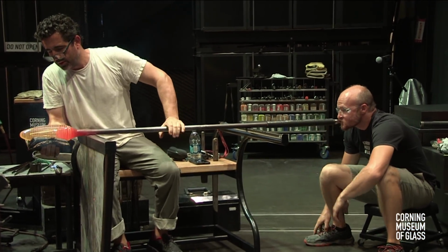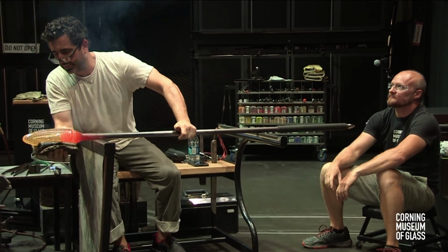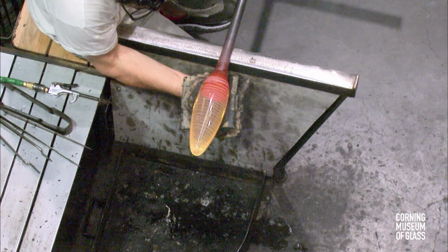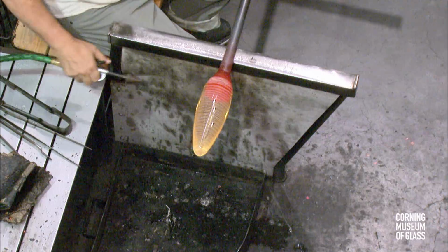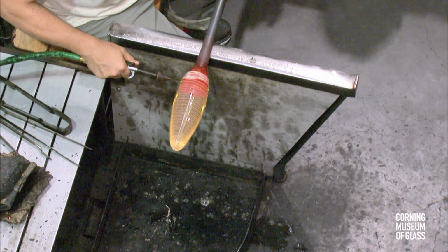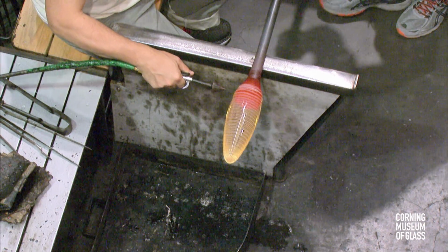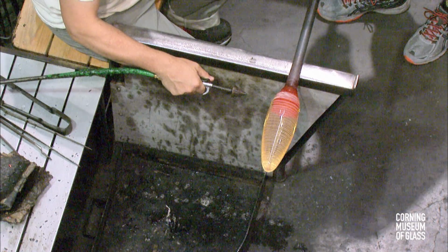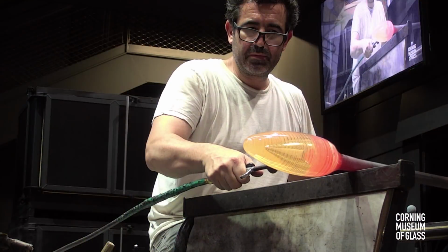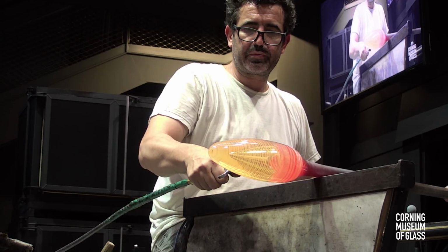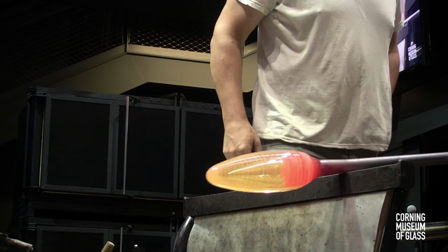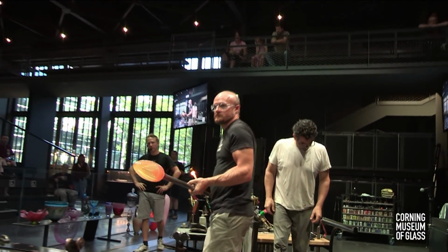They annealed it, and then they reinforced the mold. They cast it a second time. It's over 40,000 pounds of glass, so it's about 20 tons of glass, and it had to anneal for 11 months. Almost 1 year to slowly cool an object. I can't imagine waiting that long. But a giant piece of glass, one single object, just over 20 tons.